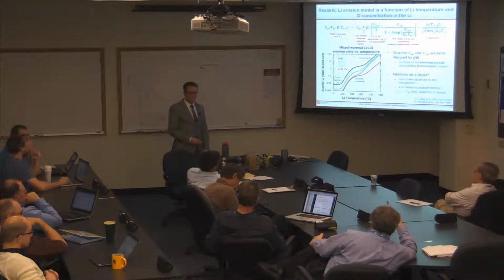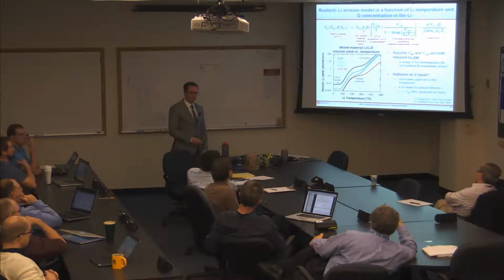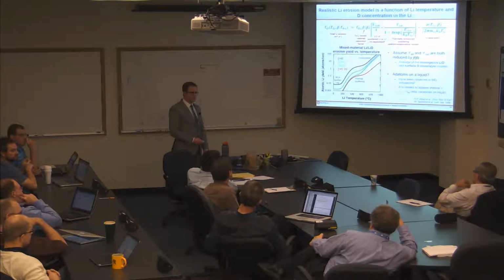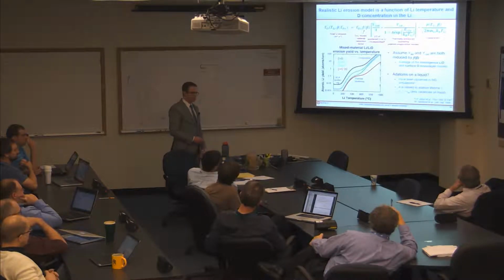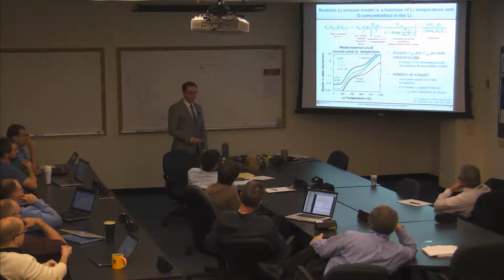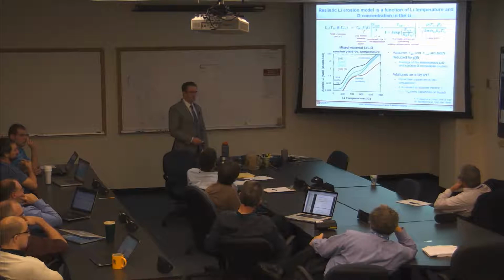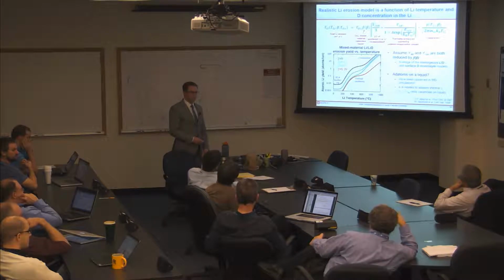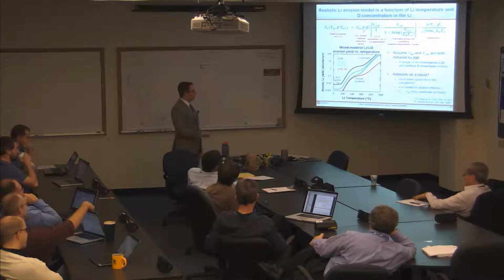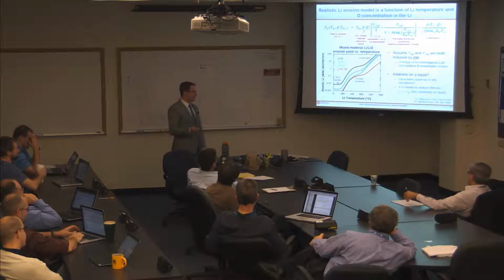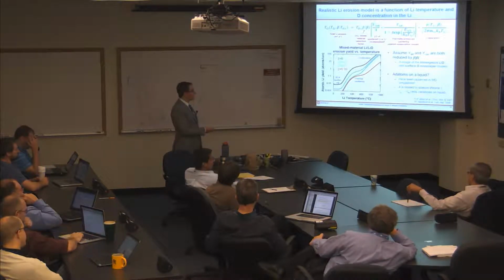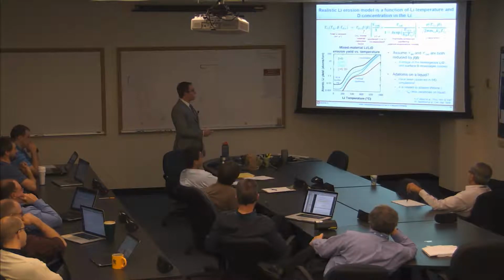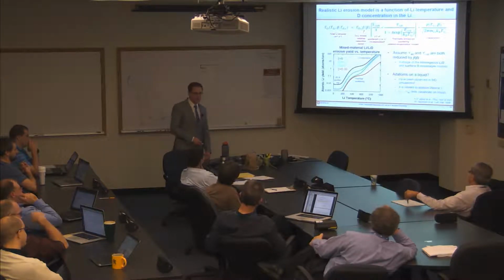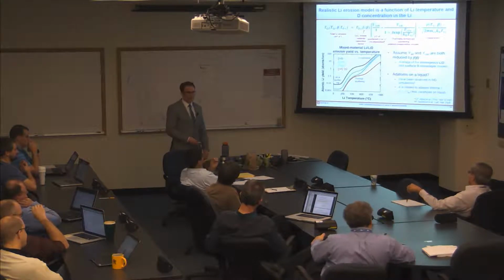You've justified multiplying F of beta times Y collisional over 3, I guess, because you did these sputtering calculations. What's the justification for multiplying it by Gardner's model? It's an assumption that I'm making. Because these adatoms are not really the same beast as the sputtering process from below, the sputtering process in the left part. I mean, it's still a sputtering process in the sense that it results from ion bombardment of a surface and it's characterized by a yield. So, like I said, it's an assumption that I'm making.